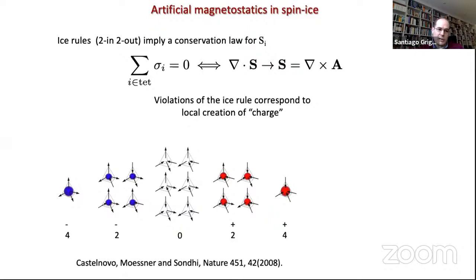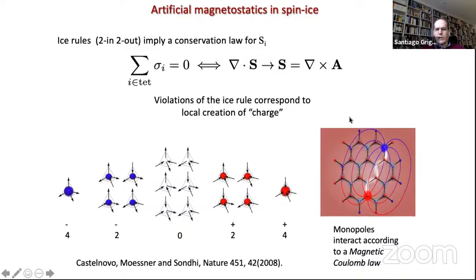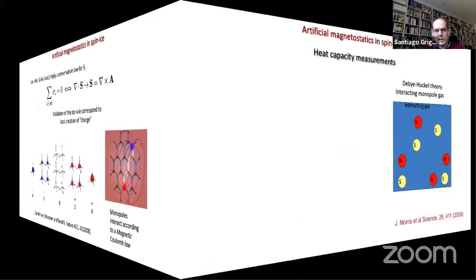If you have some sort of a Heisenberg system, you get more flavors of charges. You can have charges which are either positive, let's say, or negative, and you can either have single valued, so +2 here, or double valued +4, or -2 and -4. And you see that you get 8 possibilities of a single charge and 2 possibilities of a double charge. And when you look at how these charges interact with each other, you see that they obey magnetic Coulomb law. So essentially what you got is a mapping, if you want, between the excitations here and particles that look like monopolar excitations.